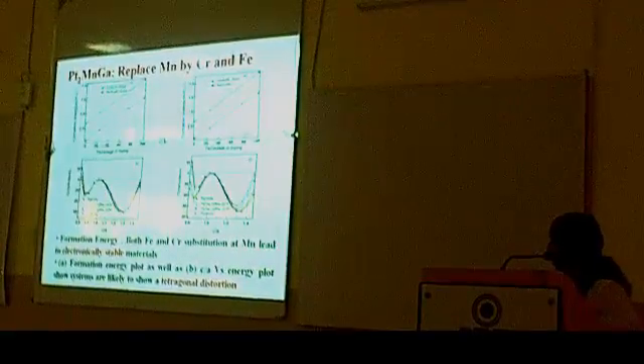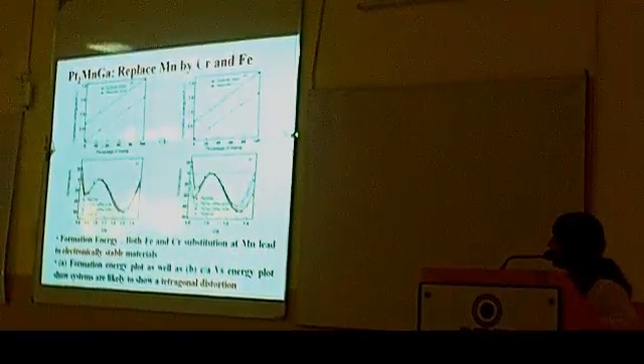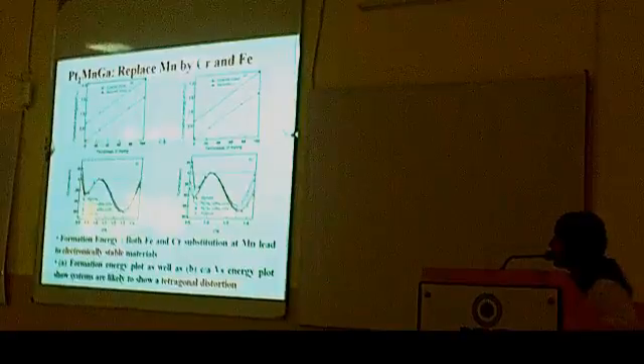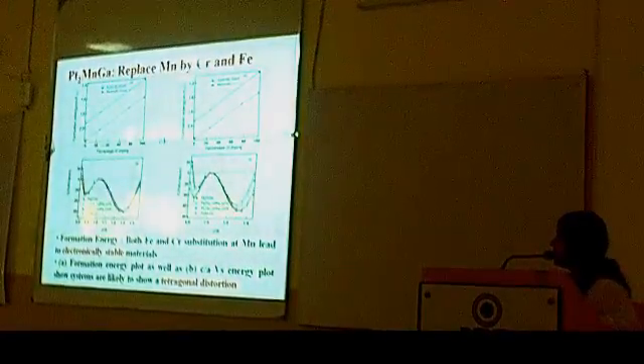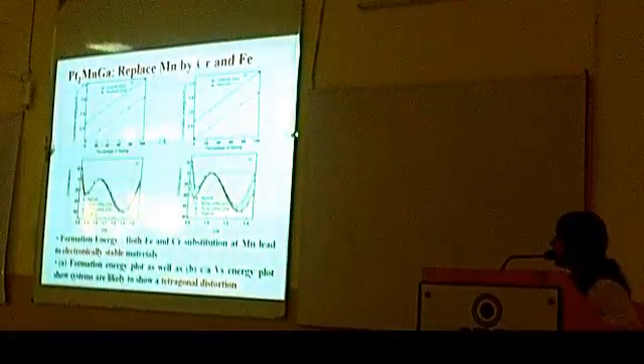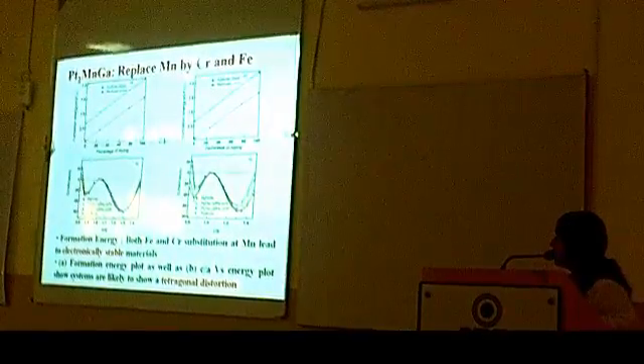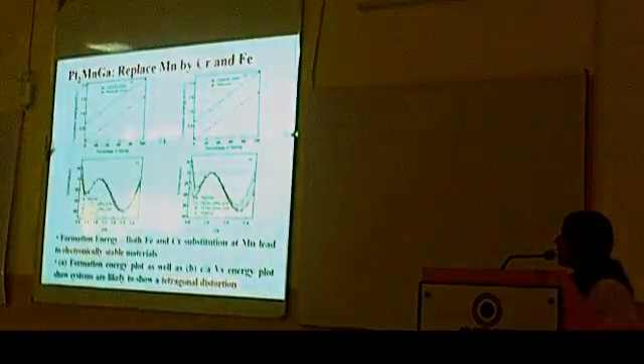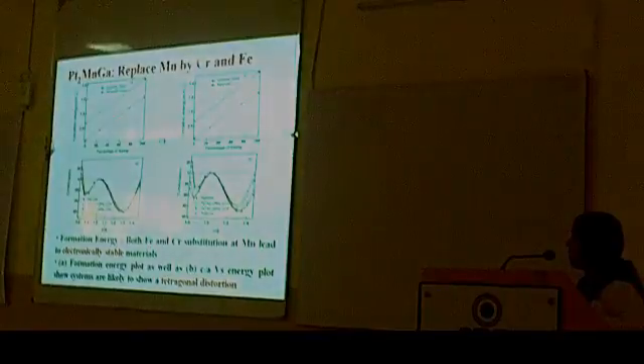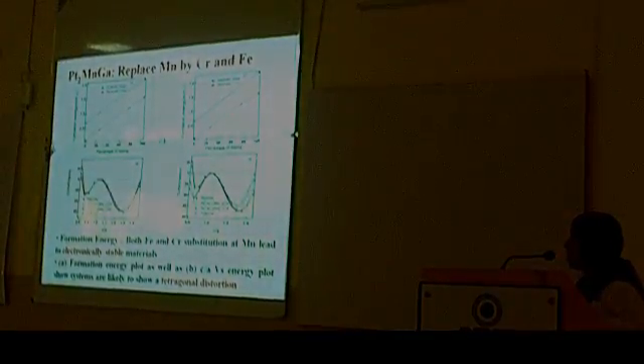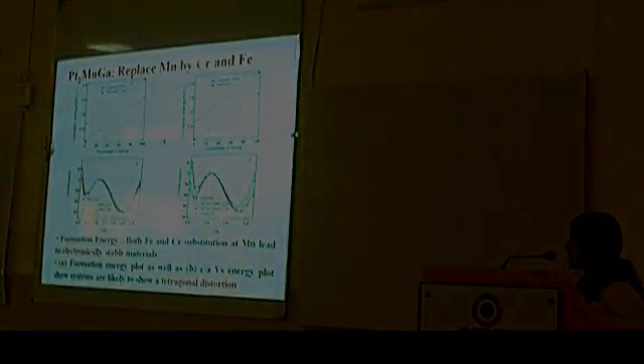Then what happens if we take a Pt2MnGa sample?, if we replace Mn by Cr and Fe, we see the same thing: the red one is the martensite, which is lower in energy, both for Cr and Fe. This also has C by A not equal to 1, having much lower energy than equal to 1, so this is also prone to tetragonal distortion.